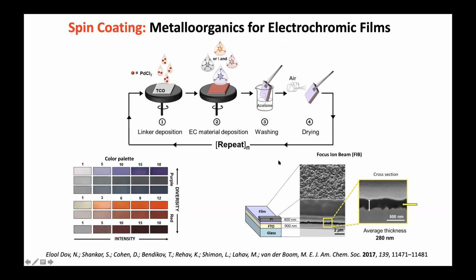We have characterized these films with many methods, but just to give an example here, we have a piece of glass. On top of it, we have a metal oxide, FTO, our thin film, and some platinum to protect the film, where we slice the film, and we see here the metal oxide. The black area is our film. It's about 280 nanometers thick. And you can see really that there are no defects and no cracks. You have really a nice homogeneous coating of your metal oxide.